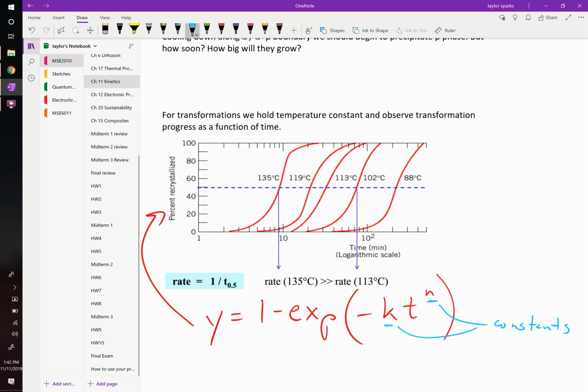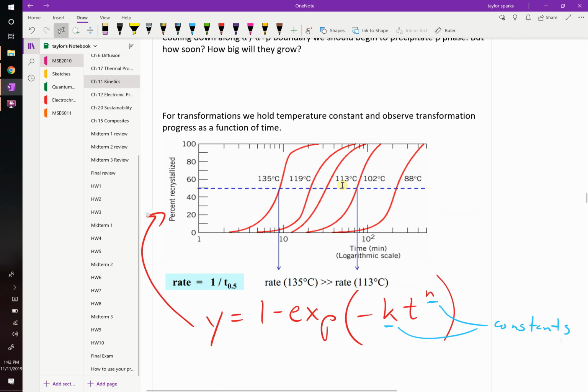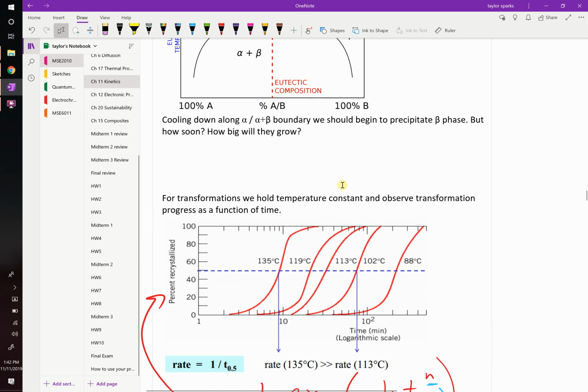Okay? Now you can see also here in polymer crystallization, what is the rate doing when you change temperature? If you do polymer crystallization at a low temperature, it might take a really long time. This is 100 minutes, right? It's barely even started to transform after 100 minutes. But you take that exact same polymer batch and you heat it up over here to 135, and it's finished by 30 minutes. It's already done, okay? So these kinetic processes are temperature dependent, okay?